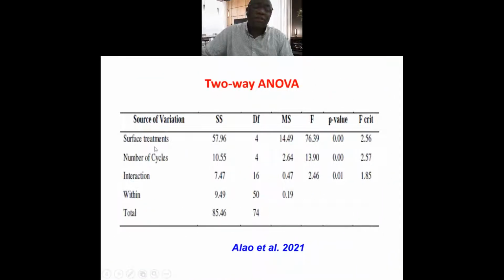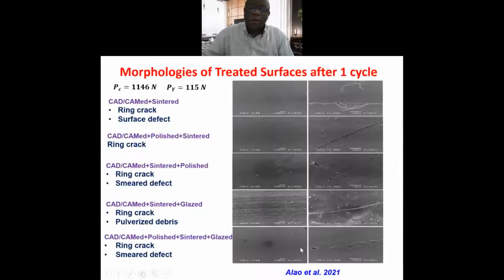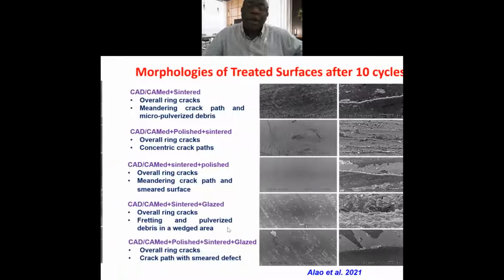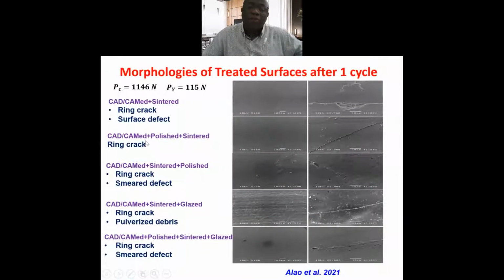So this is a two-way ANOVA carried out in order to test whether the surface treatment and the number of cycles influence the contact stress. You can see the p-value for the two is 0, which means the two significantly affect the contact stress. So these are the surface morphologies at different cycles. After one cycle, you can see the ring cracks, but for the polished sintered it is almost not visible. But when we increase the magnification, you can see the ring crack.